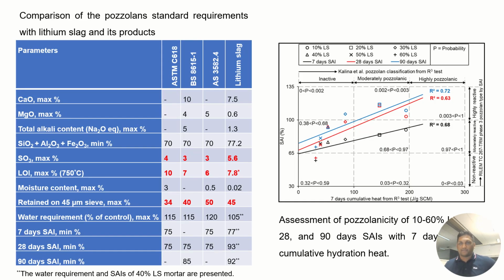The pozzolan requirement for lithium slag also satisfied the ASTM, BS, and Australian standard pozzolan requirement. Here we can see that the sulfate was higher, but it still will not pose an internal sulfate attack threat because the C3A phase of the cement has been decreased with the increase of the partial replacement of cement. The loss on ignition has been increased to 7.8%, which is higher than the BS and AS standard, but within the ASTM standard.